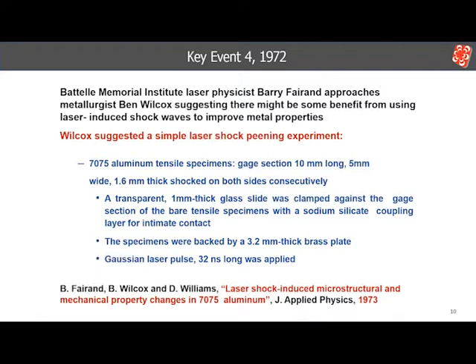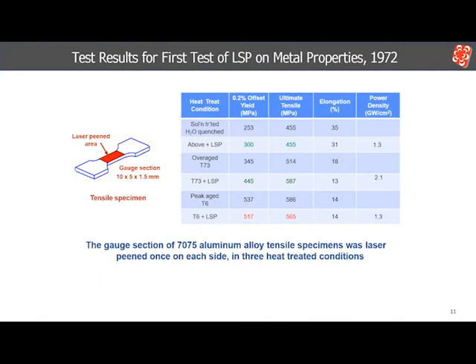Wilcox suggested a simple experiment of laser shocking several thin aluminum alloy tensile specimens having different strength properties due to different heat treatments, and determining whether there was a resulting change in strength and ductility. This experiment resulted in the first publication of laser peening. The tensile specimens were 7075 aluminum, 1.6 millimeters thick. They were shocked with one shot on each side with a 32 nanosecond pulse through a glass overlay and backed by a 3.2 millimeter thick brass plate.